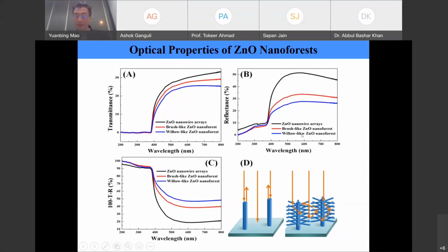We published it before, but I see there's a typo. The willow-like zinc oxide nanoforest actually has the lowest reflectance. So we know that if we subtract the transmittance and the reflectance, we get the absorption. Based on that, we will see that the willow-like zinc oxide nanoforest gives the highest absorbance, and the zinc oxide nanowire arrays give the lowest absorbance.